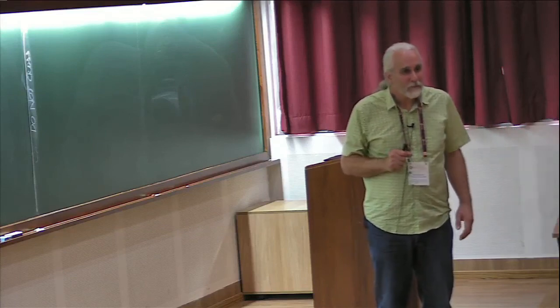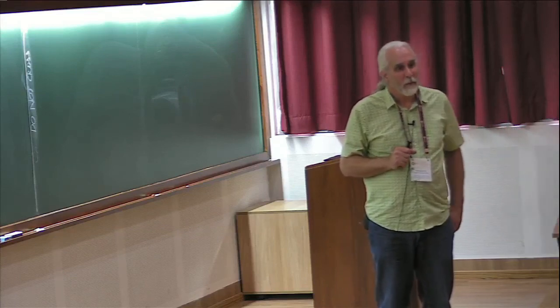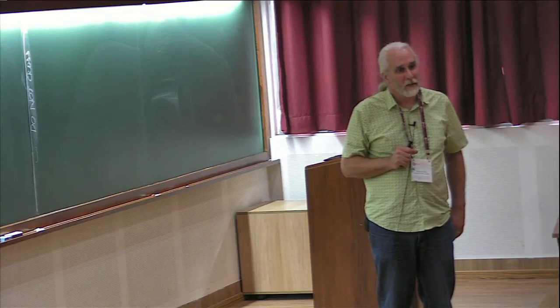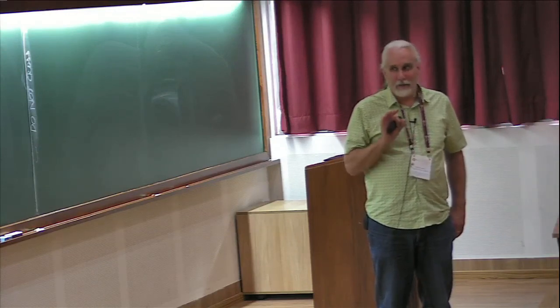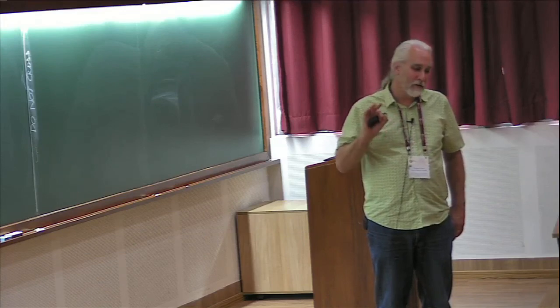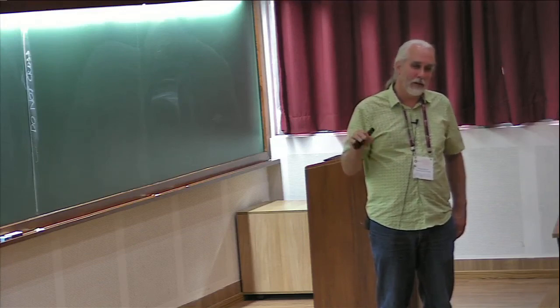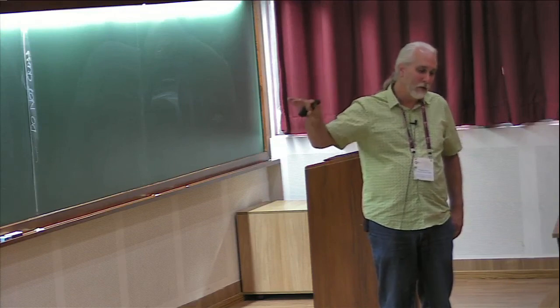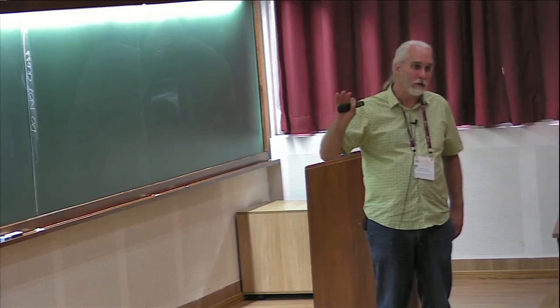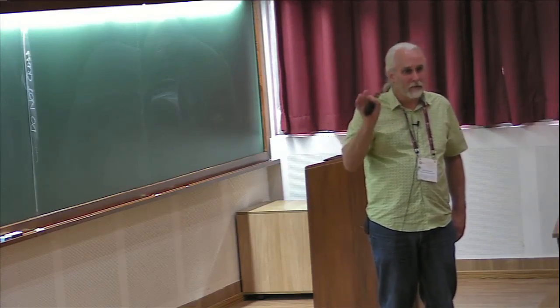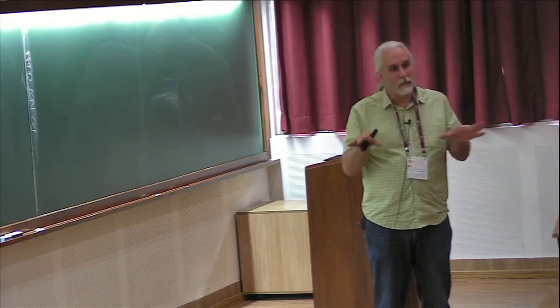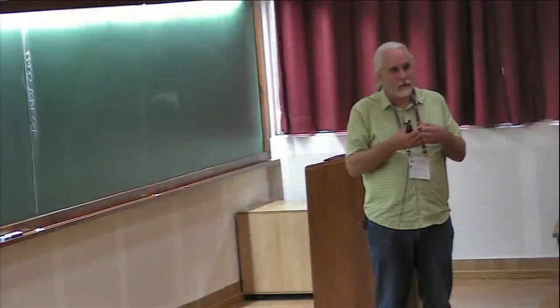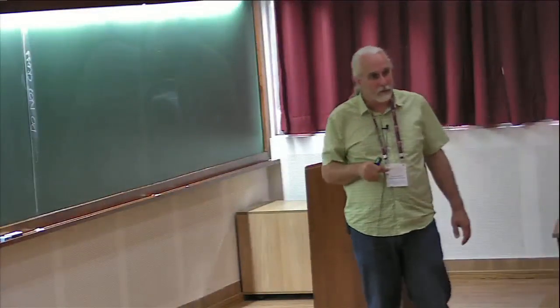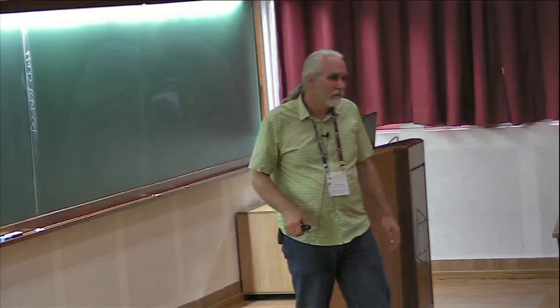Very experimental question. You used F4TCNQ for doping. Yeah. That's somewhat unconventional for an inorganic system like this. It's our whole dopant of choice, and this thing has such a low work function that probably anything that you put on it would hole dope it, but at least it's a molecular dopant, so it probably is weakly interacting, right? It's less likely to form some covalent bond and some strong defect or something. Okay. Yeah.